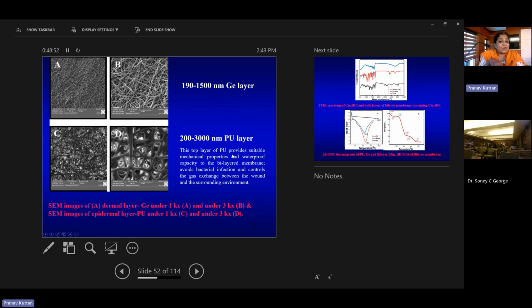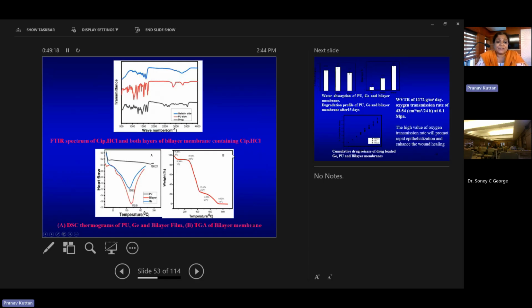And it has this porous structure, which is very, very important for wound healing. So this top layer of PU provides suitable mechanical properties and waterproof capacity to the bilayered membrane, which avoids bacterial infection and controls the gas exchange between the wound and the surrounding. The first one is the infrared spectrum of ciprofloxacin. We can see that the characteristic peaks of ciprofloxacin are seen in both the membranes, so it is confirmed that it is distributed in both the membranes. DSC and TG were also evaluated to confirm the properties of this drug.